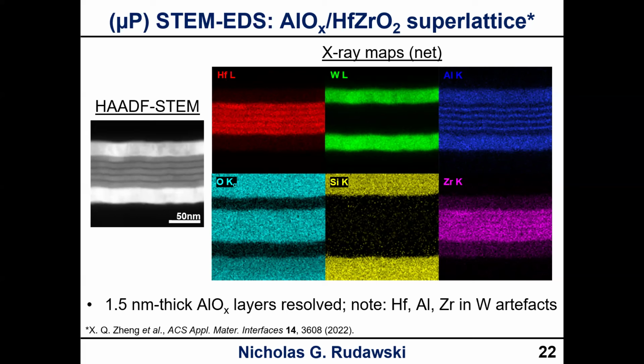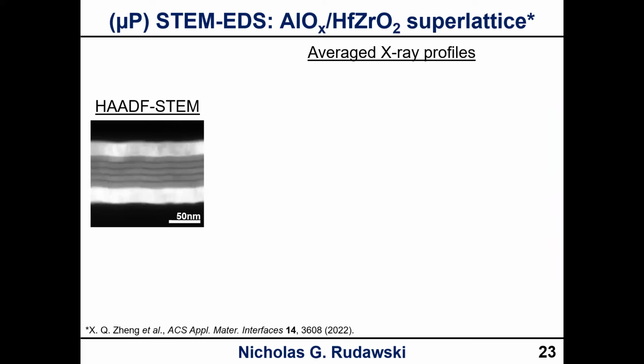That's because the rest of those maps are fitting an entire X-ray family, and there's more than just an alpha peak involved. But the point is, even in microprobe STEM, and again, this was with almost 2 nanoamps of current, we can resolve those really thin alumina layers.